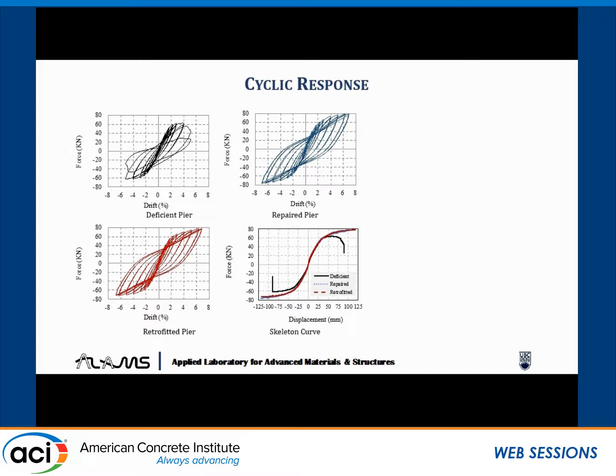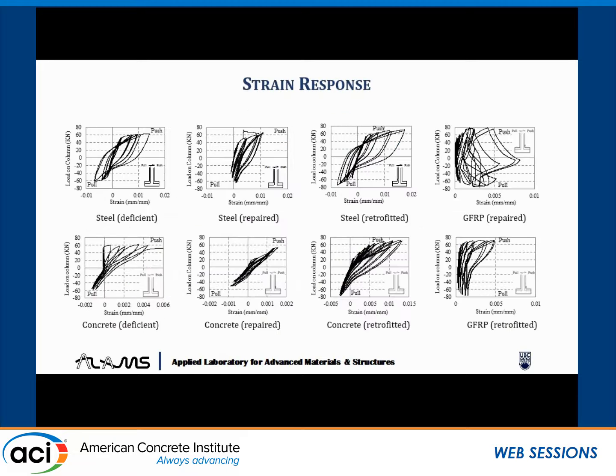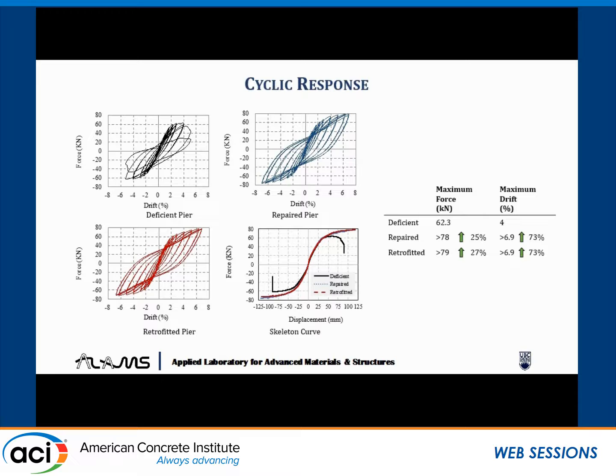And these are the backbone curves. So if you look at the deficient pier, this was the capacity, and the capacity of the others was, we said, more than this, because if you had a larger stroke length, it kept increasing. So we saw more than 25% increase in capacity, and for this one the maximum was 4% drift, whereas it could go even beyond. So 73% increase in the drift capacity.